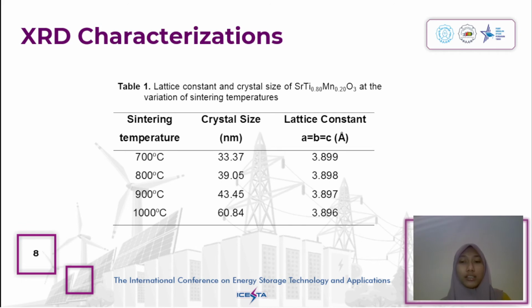Next, in table 1, the lattice constant does not change significantly as the sintering temperature gets higher. Commonly, sintering does not affect the crystal structure, which is indicated by the unchanged lattice constant. However, sintering temperature affects the crystal size, which increases with the higher sintering temperature. Besides providing sufficient energy to react, high temperatures also increase atomic mobility, which promotes grain growth. This condition also results in better crystallinity.